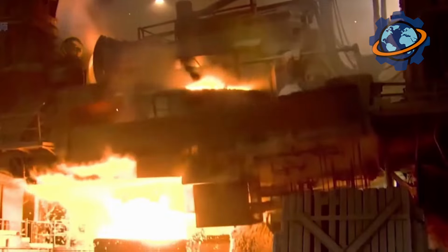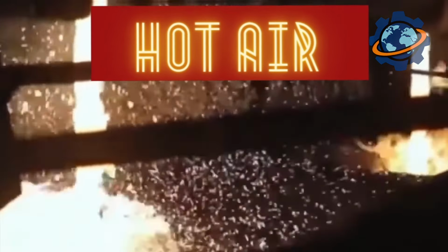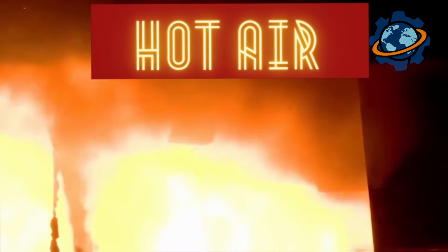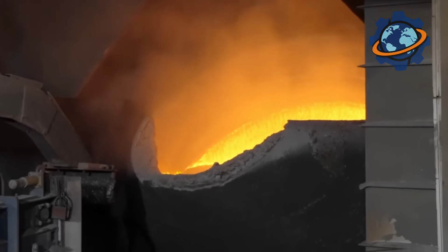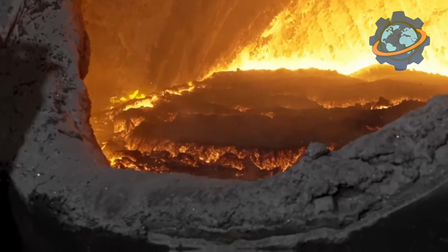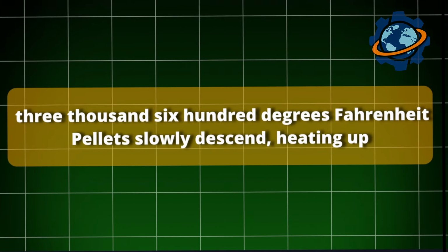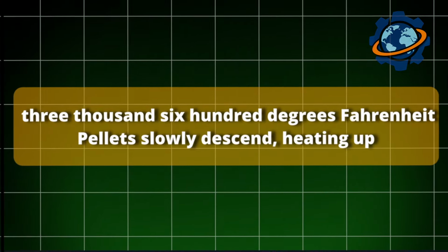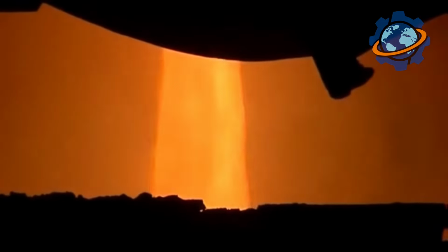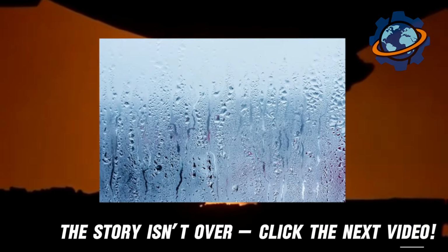From below, through tuyères, openings in the walls, hot air is blown in. Air temperature, 2,200 degrees Fahrenheit. Pressure, 4 atmospheres. Coke ignites. Temperature in the furnace's lower section reaches 3,600 degrees Fahrenheit. Pellets slowly descend, heating up. Different reactions occur at different heights. First, moisture leaves the ore.